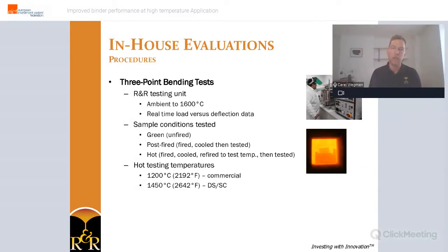Tests were carried out at 2 temperatures. At 1200 degrees C, which represents the average shell temperature after casting steel in a typical commercial foundry, and at 1450 degrees C, which represents the typical temperature in an aerospace foundry.